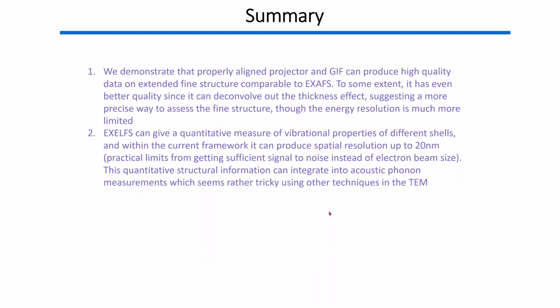And this extended electron energy loss fine structure can give us, as we talked before, a quantitative measure of the vibration property of different shells. And within the current framework, I think we can pretty much reach spatial resolution up to 20 nanometers, roughly. When we say this, it's not because we're limited by any probe size, we're really limited by the signal to noise, which is the killing factor for the moment. And using this, we can couple this into acoustic phonon measurements.